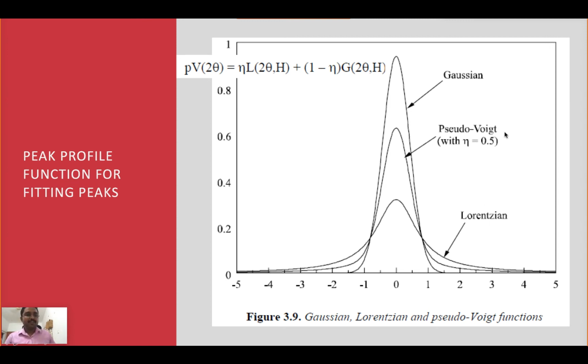Since the Voigt function is not able to be produced computationally, what we have used is the pseudo-Voigt function. Completely through computation, the Voigt function is not generatable. So what they are using is the pseudo-Voigt function. If you use this particular function, it will give a better fitting for your asymmetrical peaks, where the peaks will not have the same slope. We will see that.